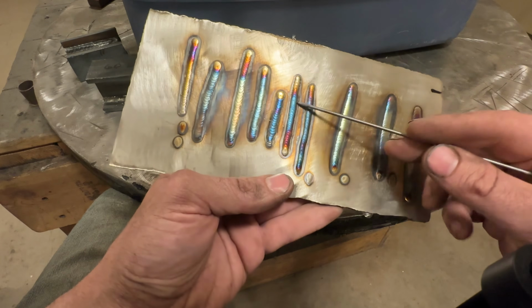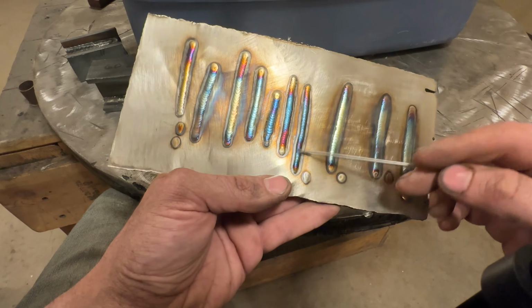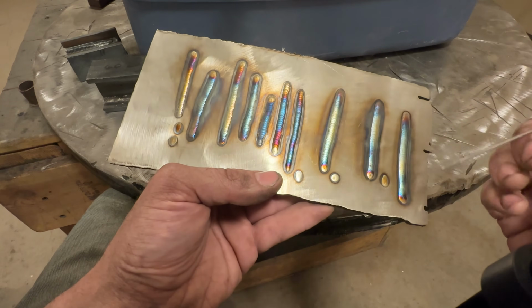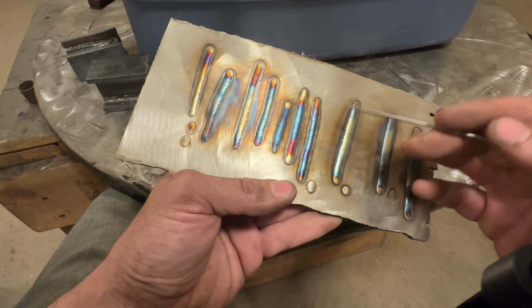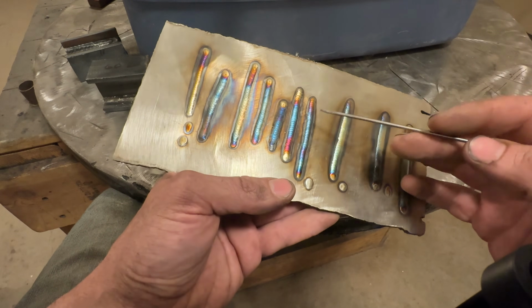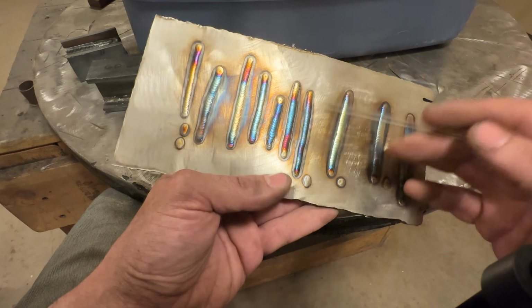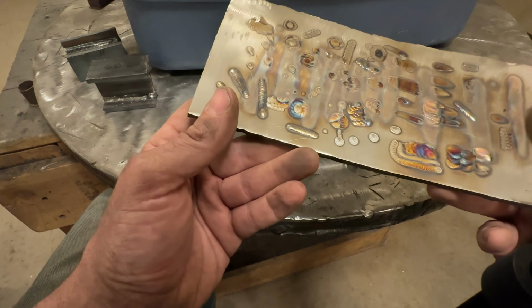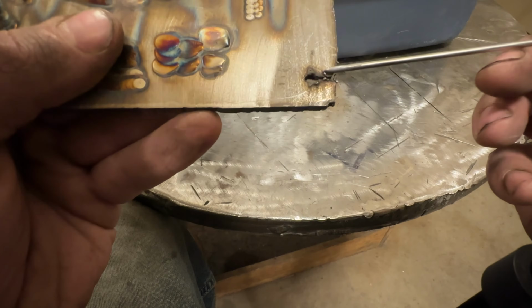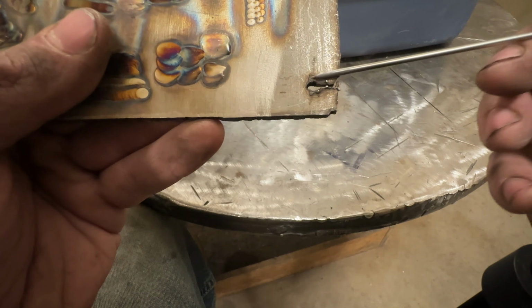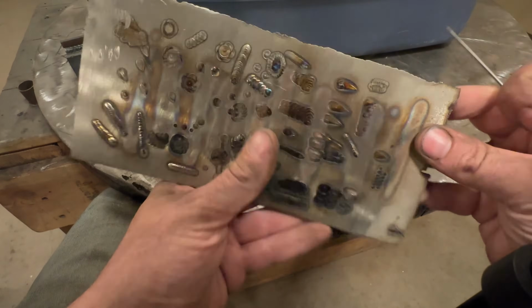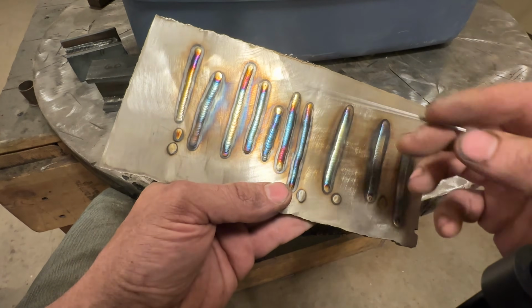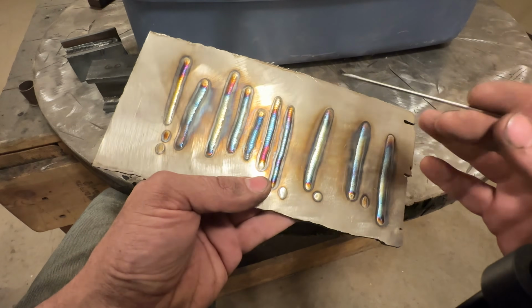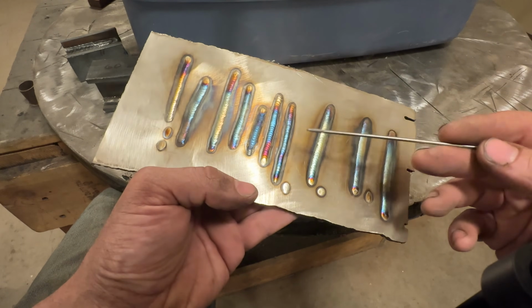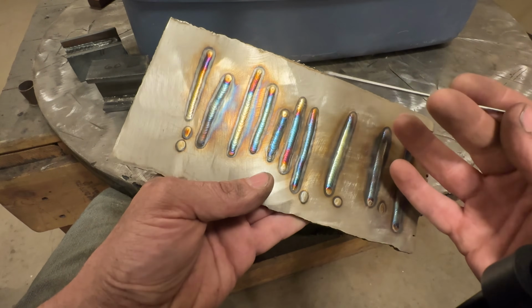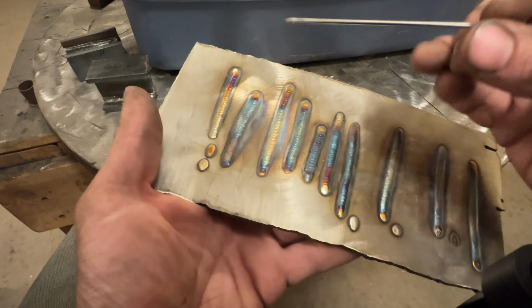Now, you can passivate and clean this off. I could mechanically wire brush this to clean it, but in sanitary situations, they'll clean this with an electrolysis process. But if it's dull gray and cooked, like I don't really see any on here that are a good example of that, like if you look here where it was plasma cut, if your welds are dull and gray and look like that, you can't passivate that with a cleaning solution in an electrolysis machine or whatever they're called. So that would be completely unacceptable. A lot of this you may be able to clean up, but again, it all depends on what you're welding it for. Now, TIG is much, much harder to tell.